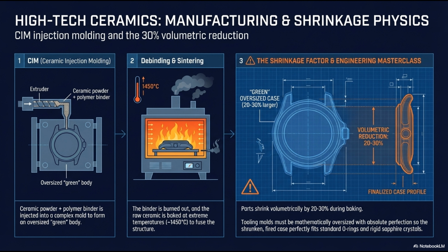This is an engineering masterclass. As the binder burns away and the particles fuse, the parts shrink volumetrically by a massive 20 to 30% during baking. Look at the diagram comparing the oversized green body to the finalized case profile. The engineering nightmare is this: the tooling molds must be mathematically oversized with absolute perfection so that the violently shrunken, fired case perfectly fits standard, zero-tolerance O-rings and rigid sapphire crystals. If the math is off by 1%, the case is scrap.